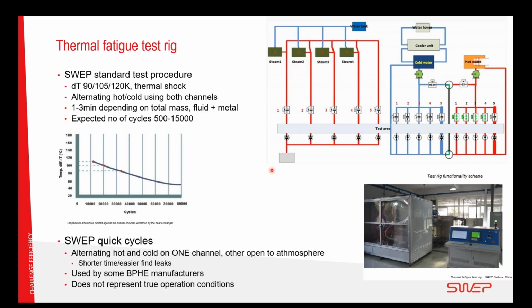So what we have created is this SWEP standard test procedure, where, taking from the chart on the previous slide, we have the temperature differences of 90, 105, 120 K. And then we are alternating the hot and cold, and we are using both channels in the heat exchanger. So the one fluid is standing still, while the other, the hot one, is being pumped, and this is done 1 to 3 minutes depending on the total metal mass, and also the volume of the fluid on the other side. So everything is then being heated up, and then we close the hot loop, and then we shock it thermally by opening the cold water into the heat exchanger to get the thermal shock here.